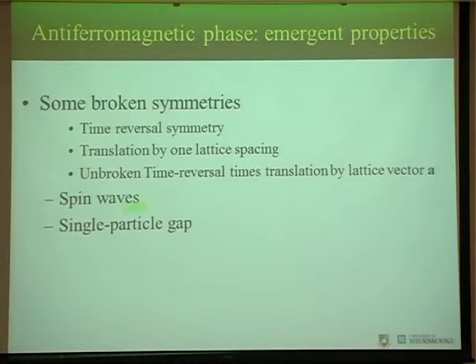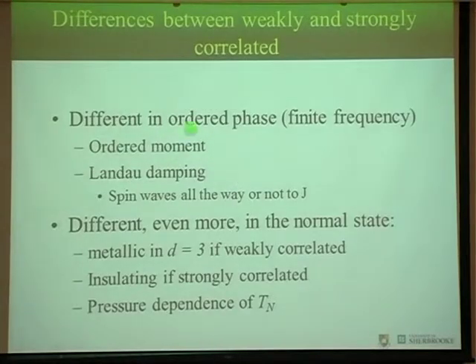I'm coming back to superconductivity in a minute, but I step back with the antiferromagnetism. An antiferromagnetic phase breaks symmetries: time reversal, and translation by one lattice spacing, while the product of the two is conserved. And if you have an antiferromagnetic phase, it necessarily has a spin wave at asymptotically low energy and a single-particle gap at least somewhere in the zone.